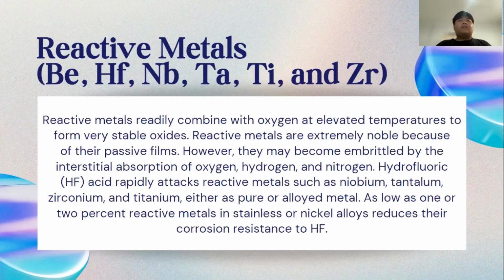Reactive metals. Reactive metals readily combine with oxygen at elevated temperature to form very stable oxides. Reactive metals are extremely noble because of their passive films. However, they may become embrittled by the interstitial absorption of oxygen, hydrogen, and nitrogen. Hydrofluoric or HF acid rapidly attacks reactive metals such as niobium, tantalum, zirconium, and titanium, either as pure or alloyed metal. As low as 1 or 2% reactive metals in stainless or nickel alloys reduce their corrosion resistance to HF.